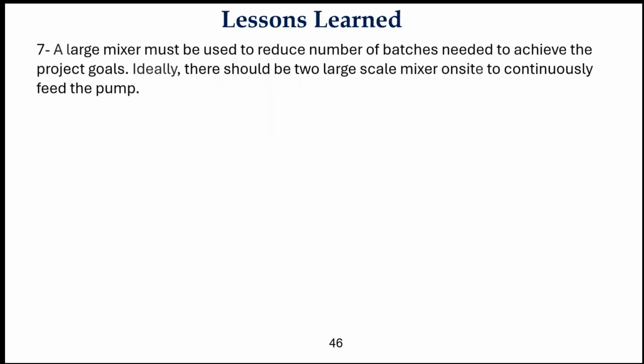This is important for UHPC, and this is general, not just UHPC, for the spray. You have to use a mixer that can put lots of energy. In fact, we took all the equipment with us except the mixer, and we asked the Virginia DOT to give us the mixer. The mixer was a little bit small. We couldn't mix more than 8 cubic feet, and that was the limit, which actually filled up the mixer. So the rule of thumb is, if you want to use a mixer that is used for conventional concrete, you really should not be mixing more than half the capacity of the mixer if you're using it for UHPC. Try to get a mixer that is specific for UHPC, with paddles in a format that puts lots of energy into the mix.